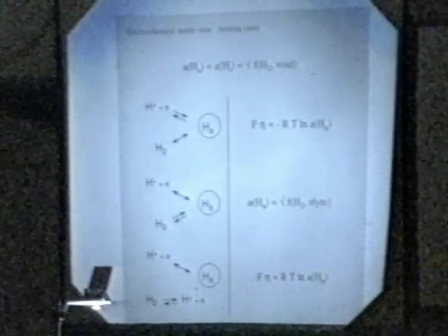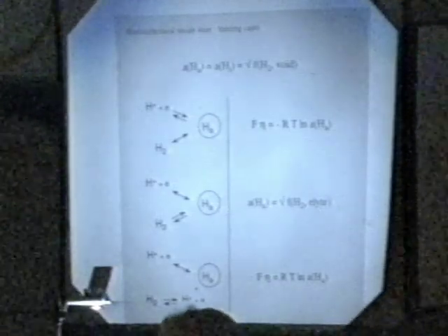This is an extreme case. It may not ever be attained in practice, but it's a limit. So, for example, in this case, we will assert that the Volmer step is in a state of quasi-equilibrium, but the Tafel step is not. In other words, most of our overvoltage is going into pushing a reluctant Tafel step forward.